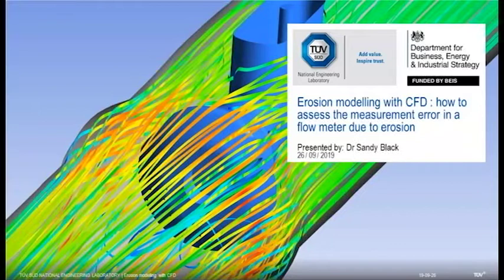So we have a question about the roughness of surfaces considered in the model. Typically, the roughness of the surface is not considered in the model, but we can do. Most of the time, we don't really know what the roughness of the surface is, but it is something that we could measure. I imagine it would have a little bit of an impact, but it depends on the particle size and what you're looking at. So if you have a couple of microns roughness, but your sand particles are 1 millimeter, then it's likely that it's not going to make a significant difference.